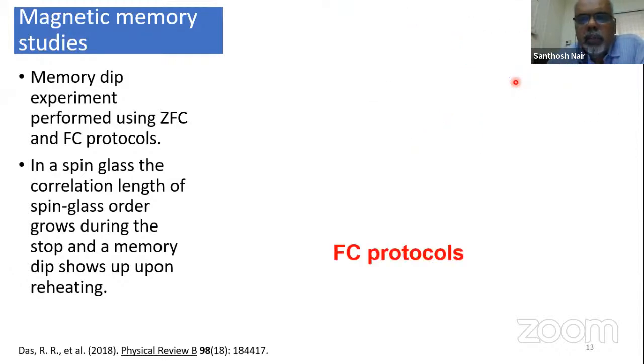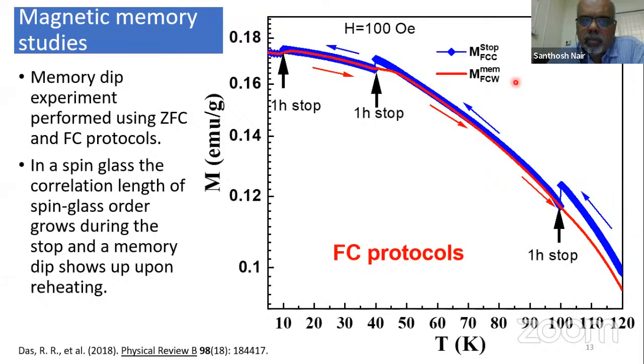So you can do a similar thing with a field cool protocol where you do the same process in the presence of a field. So wherever you have kept the system halted, you see these signatures of where the system remembers. But we also did it at higher temperature. So these were done at low temperature where you see in the magnetization curve we have a second transition. At a higher temperature, where a ferromagnet is involved, we do the same thing. We don't see any memory effect. So it's seen only at very low temperature. So the glassy phase exists at very low temperature.